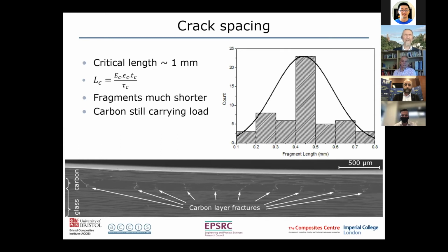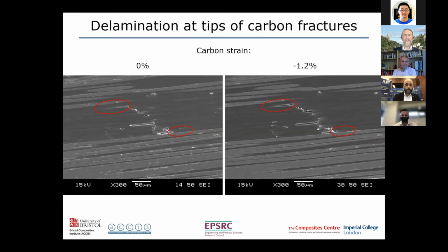So I guess that's not surprising because they're in contact. But then the question is, well, how do we get this additional strain if they're in contact and still carrying load? So to look at that, let's look at this magnified version of what happens at the crack tip. Here you've got an angled crack, here unloaded, and if you look at the interface there, you can just about see there's a delamination which is starting, but it's closed. But if we put the strain on at 1.2%, then you can see that delamination has opened up, and the same down here. So what's happening is we're getting a wedging action, which is causing that delamination to open up.